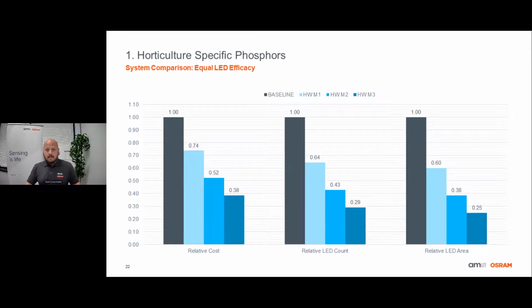Both the M2 and M3 bins had fewer than half the number of LEDs than the baseline. And this reduces the area by up to about 75%. Now, you still have to manage the same amount of heat as the system efficacy hasn't changed, but the significant reduction in area could enable you to potentially optimize your fixture design that could lower the mechanical costs or potentially modify the shape in a way that could reduce shadowing in a greenhouse installation.